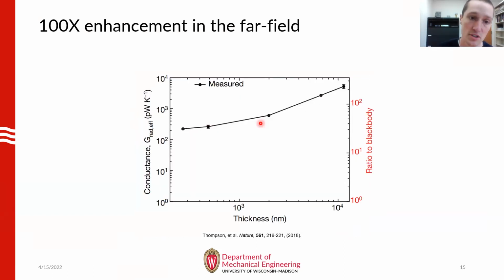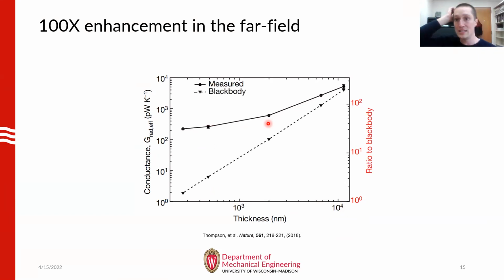Here you can see the central results, where we plot the measured radiative conductance between the emitter and the receiver as a function of their thickness. The basic trend is that as the thickness drops, the conductance drops as well. This is what you would naively expect, or at least what I expected initially. What's interesting, though, is when you compare this to the estimated black body conductance between the devices, which here is captured by the dashed line. This black body conductance was accurately estimated using a finite element model, which accounted for the exact geometry of the membranes, including their support beams, and it basically assigns an emissivity of 1 to each surface.